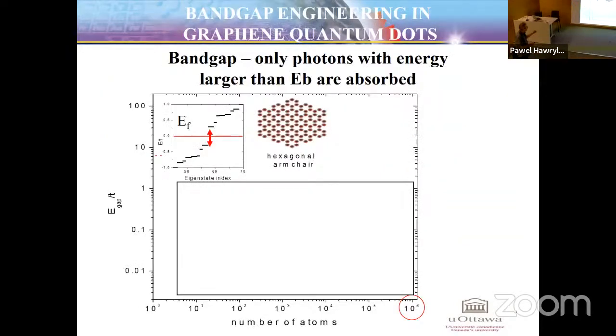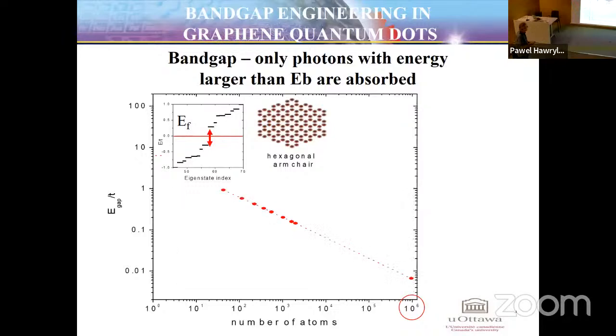So now we take different sizes and we plot this band gap as a function of the number of atoms, which is related to the size, of course. And if we look at the highest energies, we cover the ultraviolet, and then we go down to the terahertz. So just changing the size of this graphene quantum dot allows us to cover a very broad photon energy range. So perhaps this could be very useful for photovoltaics.